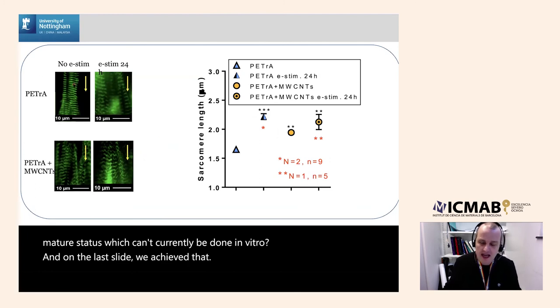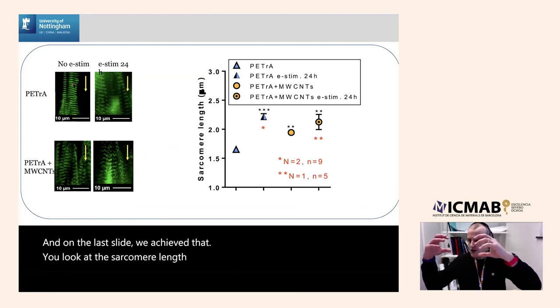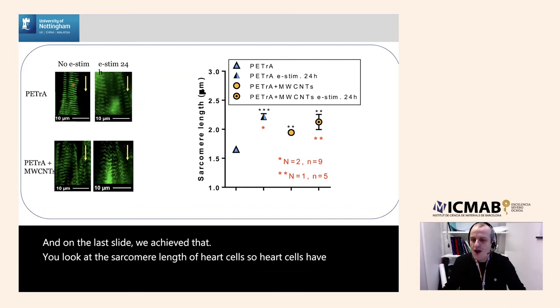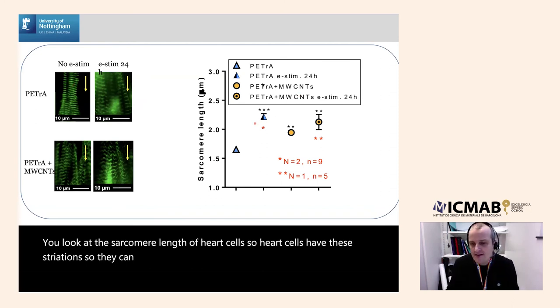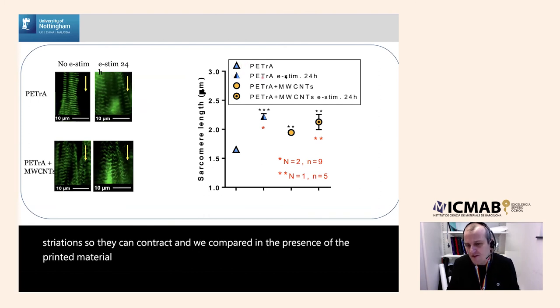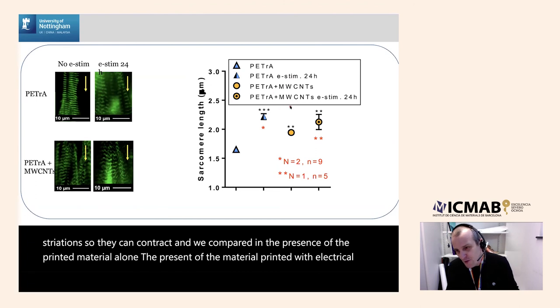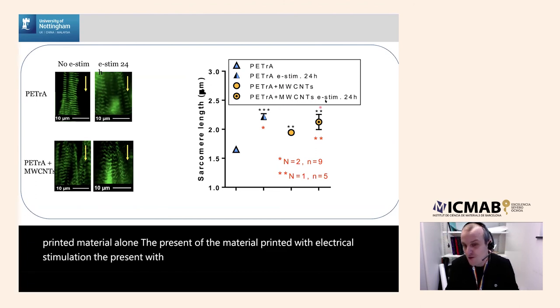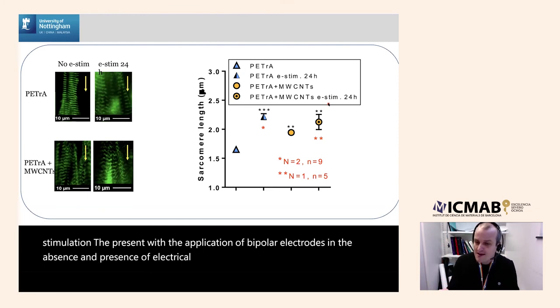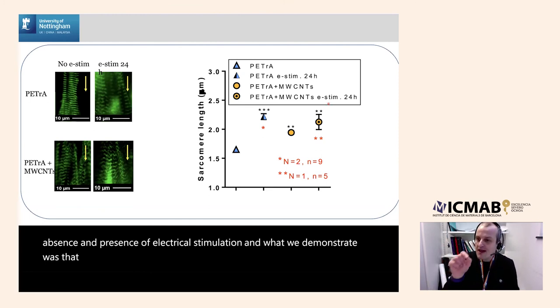You look at the sarcomere length of heart cells. So heart cells have these striations so they can contract. And we compared, in the presence of the printed material alone, the presence of the material printed with electrical stimulation, the presence with the application of bipolar electrodes in the absence and presence of the electrical stimulation. And what we demonstrated was that the electrical stimulation in combination with the bipolar electrodes caused an enhanced maturation effect in the cells.